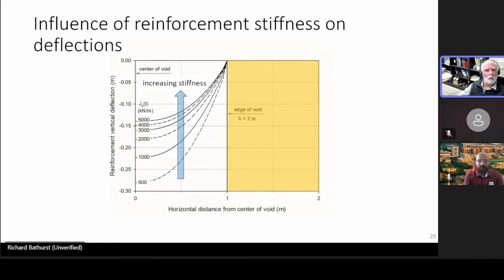And here is an example of some numerical results. What you're looking at is a half width of the void. Okay, so the 0 is the center of the void, and 1 meter in this particular example is the edge of the void. And here we've run a number of simulations where the only thing that was different between each simulation was the stiffness of the reinforcement. And what you can see is that as the reinforcement gets stiffer and stiffer, the deflection at the bottom of the fill surface at the elevation of the reinforcement becomes less and less. And this is in sympathy with our expectations.